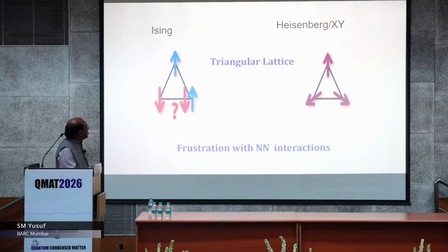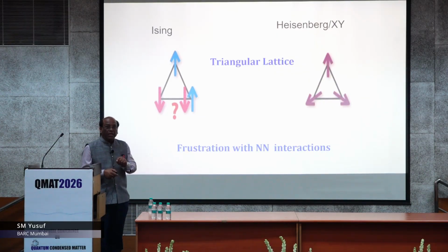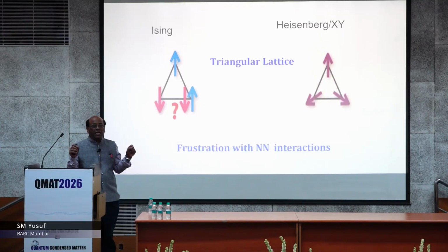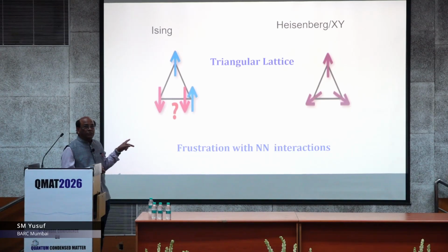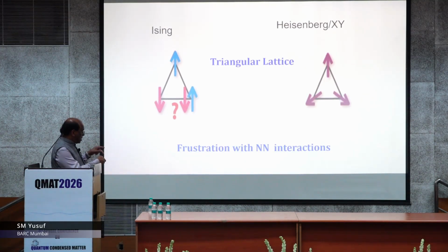So in this triangular lattice, I must tell you that exchange interaction is there, but this particular spin is frustrated due to its geometrical constraint. The point to see is that the exchange interaction between these two is negative, and the exchange interaction between these two is also negative. So the frustrated spin is not subjected to two competing exchange interactions, one positive and one negative, which we normally say. That is not the case. So this is the real example of geometrical frustration, because due to positional constraint, there is no competing exchange interaction facing the frustrated spin.